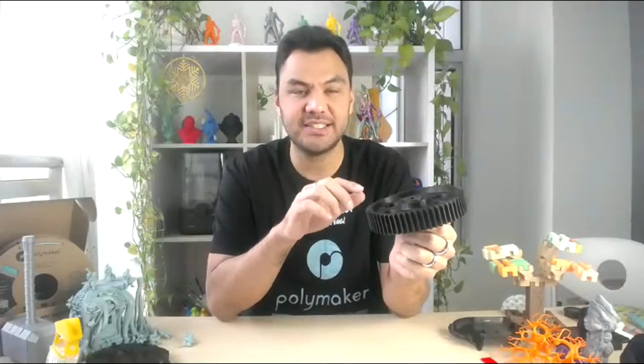For PA6 CF, it has 20% carbon fiber by weight, so it is very, very rigid. However, it absorbs much more moisture than PA12. So in the second version of our TDS, we put the PA6 CF in water for 3 days, I believe, or maybe 1 day, I don't remember, but enough to saturate with water. And then we did the same with PA12. After we compared the mechanical properties, PA12 was much higher in terms of rigidity than PA6, even though PA6 has 20% carbon fiber by weight, and the PA12 CF had 10%.